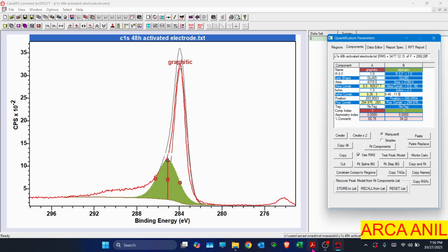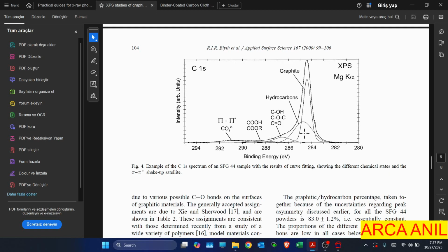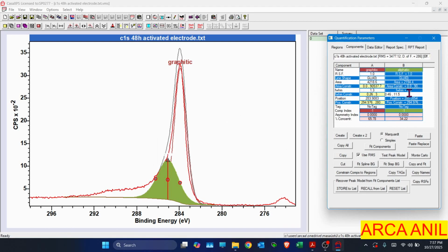And full width half maximum can be higher for this peak. As you see, it is higher. This is our aliphatic or hydrocarbons. Maybe it should be around 2.5, and we can constrain it until 3. I want to constrain the position to 284.5 maybe, and this should be something like 1 eV.